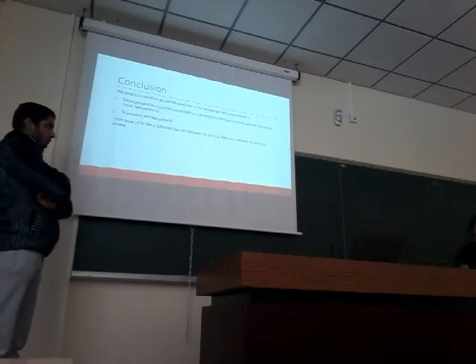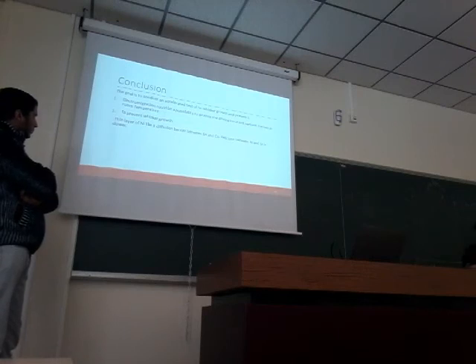So as a conclusion, as Ahmed explained before, electromigration could be a good way to perform an analysis, and can be done at room temperature. And to prevent the whiskers growth, it has been found that a thin layer of nickel can work like a diffusion barrier between zinc and copper, since the reaction between nickel and zinc is slower.